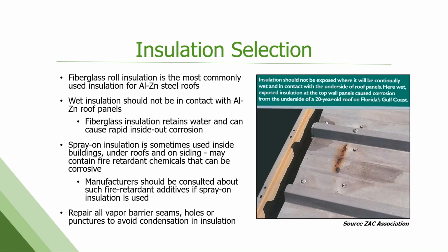Insulation. Fiberglass roll insulation is most commonly used. It's fine. You just want to make sure that it can't get wet. So if you have wet insulation on the back side of one of these panels, which is the picture here, this is a wall where water was able to penetrate and the insulation was wet. And now you get corrosion from the inside out, from the back side of the panel, because it's staying wet all the time and just corroding that coating.